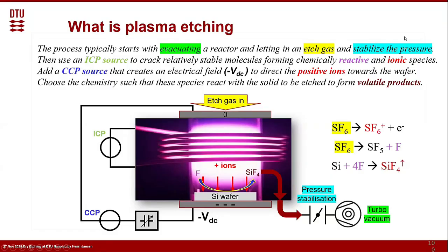Good. Then we use an ICP source to crack the relatively stable molecules, forming chemically reactive and ionic species. And we add a CCP source that creates an electrical field to direct the positive ions towards the wafer. And we choose the chemistry such that these species react with the solid to be etched to form volatile products.